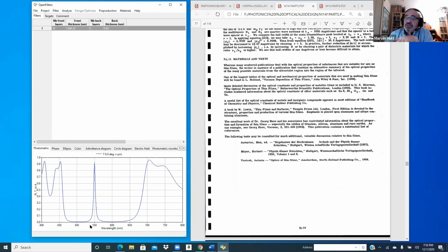The first thing, of course, is the transmission and the bandwidth that you want in the wavelength of the filter. The second, and probably the most difficult part of it, is what is the blocking? And they usually specify things like, the blocking at the low side would be less than 4 OD, density of 4, which is the log of the transmission. 4 is 0.0001.